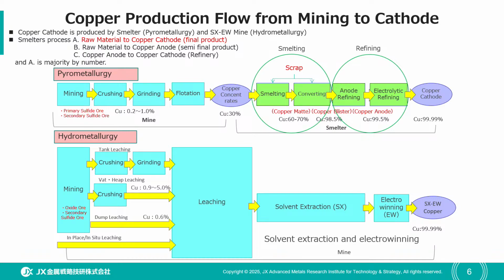from 1% to 30%. And the smelter makes copper cathode from the copper concentrate, with a copper content of 99.99%, which is 4N. And by the hydrometallurgy process, copper ingots called SXEW copper are made at the mine site, which have the same content. The process depends on what minerals you have. For example, primary sulfide ore and secondary sulfide ore are processed by pyrometallurgy, and for oxide and secondary sulfide ore, these two are processed by hydrometallurgy.